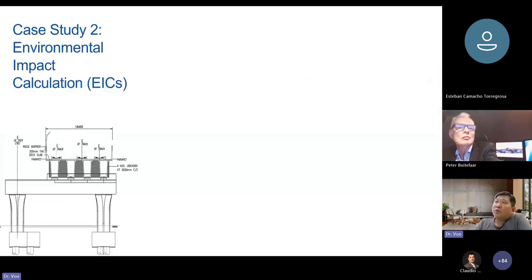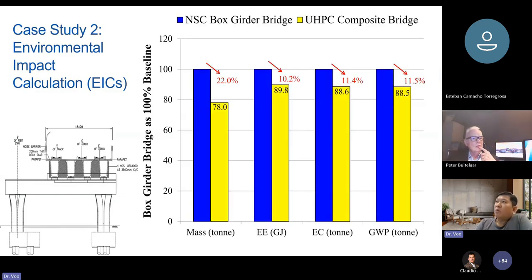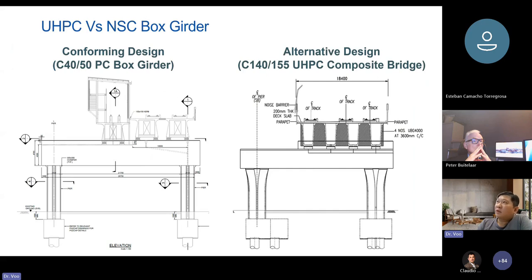So here, I would like to do another calculation, comparing this UHPC with a normal strength concrete box girder. What it shows is the UHPC composite bridge has an immediate 22% saving in terms of weight. This also includes the substructure and the foundations. Okay, and embodied energy is about 10% lower, and embodied carbon and global warming potential is also around 11 to 12% lower compared to the conventional design. Okay, and this is how the conventional or the conforming design looks like, basically using the grade 40/50 pre-stressed concrete box girder versus the UHPC system.